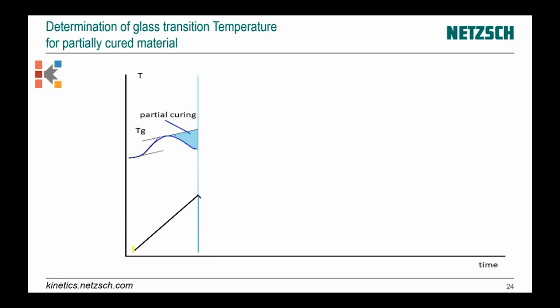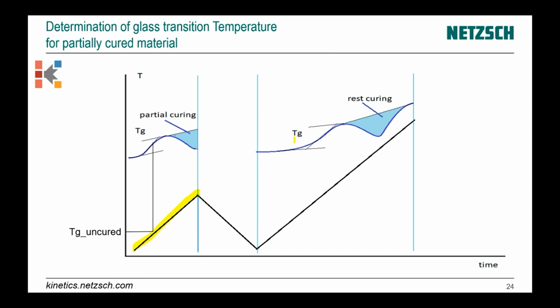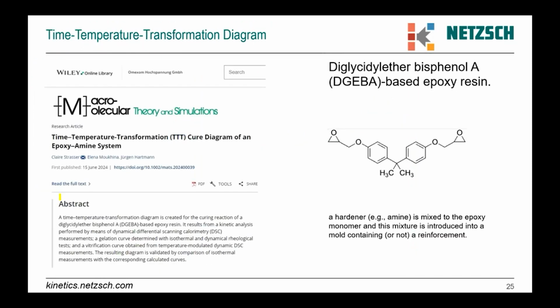Firstly, we have heating up to some partial curing. Find a glass transition of uncured material, then make cooling and heating again, and then for the partially cured material, we have another value of glass transition, and from the residual curing, we can find the degree of cure which corresponds to this glass transition temperature. And finally, we can find the dependence of how the glass transition moves from a lower value to a higher value with degree of curing.